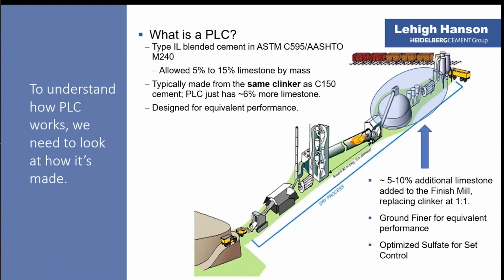So this schematic here shows what a modern cement plant looks like. And then the blue bubble, that's really the only place that you see any difference from the production process on a C150 cement versus C595. So in that blue bubble, we would take that same clinker that would go into the C150 cement. That same clinker is ground with an extra addition of about 5 to 10% extra limestone, and it's replaced in the finish mill with the clinker at a 1-to-1 ratio. Very important to understand that this PLC is ground finer, and that's necessary for equivalent performance.